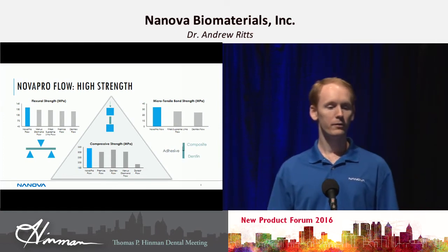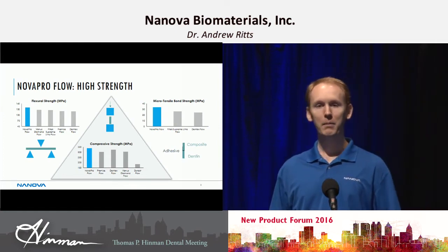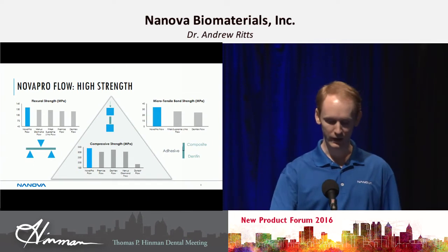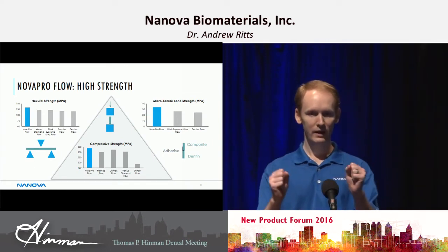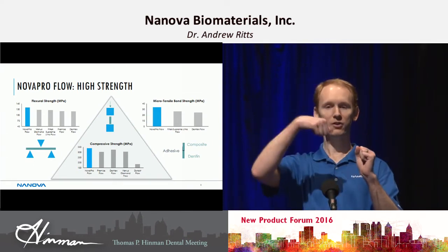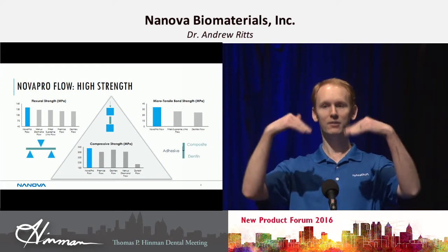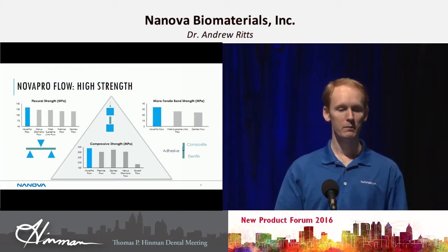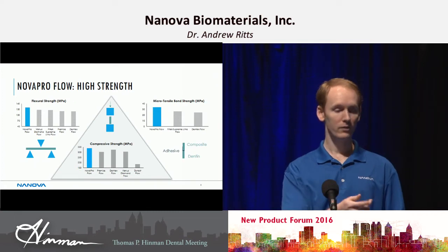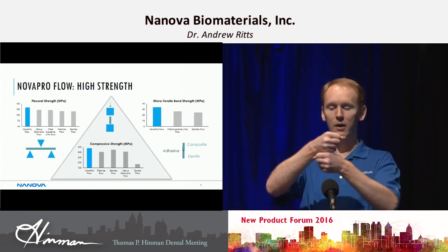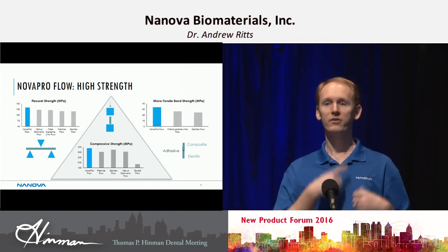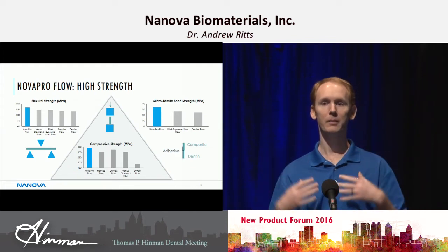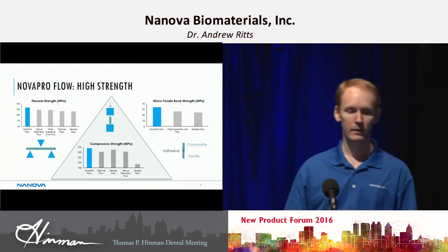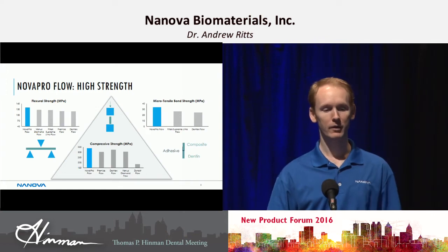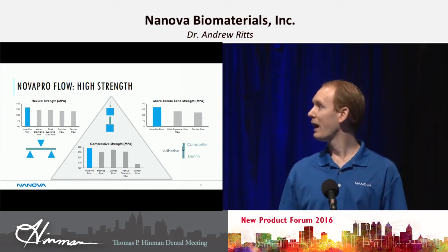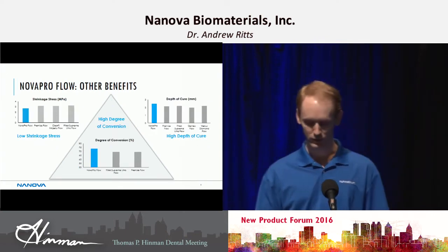You can see the NovaPro Flow high strength. When we're talking about bending strength, it's actually a 3-point bending. So you have 2 base points and then a point in the middle that pushes on it. And why that's important is it's a mixed type of failure. With compressive strength, we also have a very high value, but it's just a one-direction type of failure, whereas clinically you're going to have a mixed failure typically if you're going to have a failure of the composite. Also, we have very high microtensile bond strengths as well.